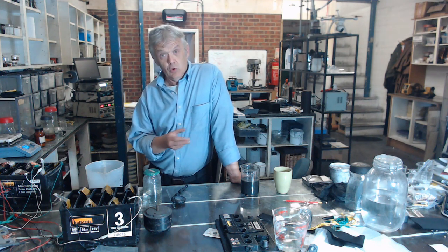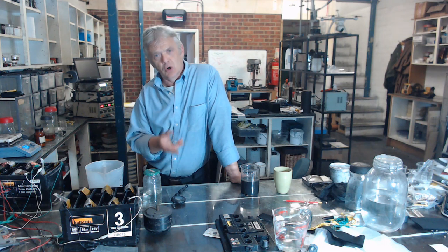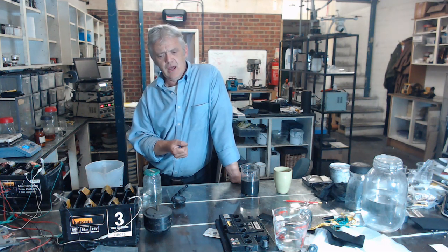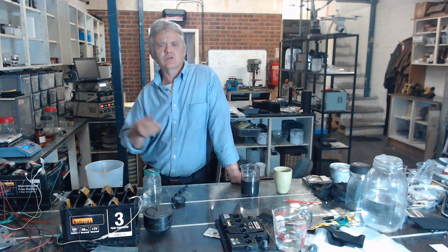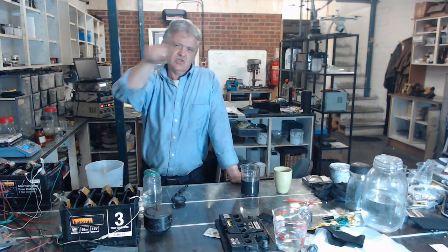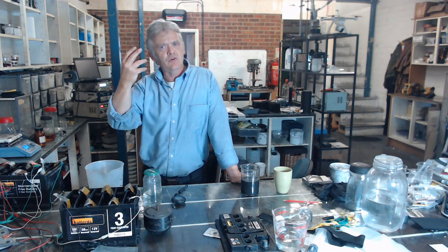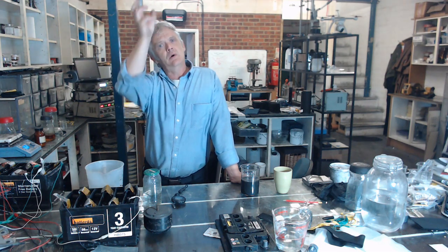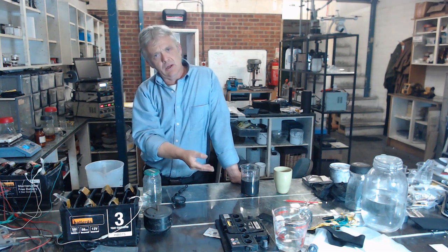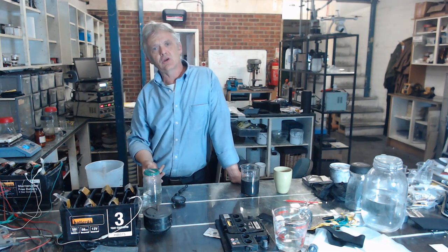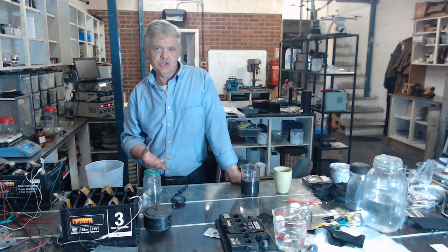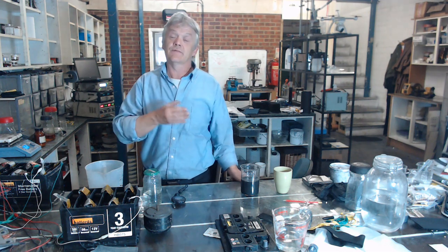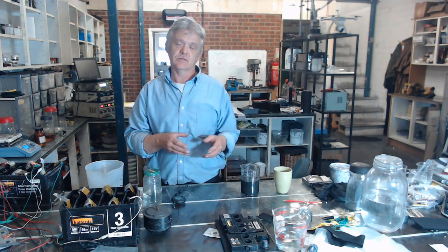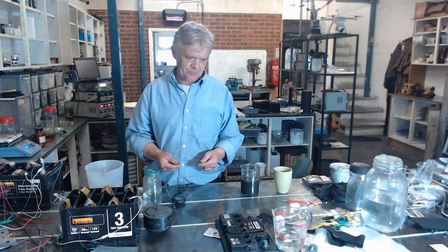Now obviously it uses a lot of water, so sometimes it's not appropriate to do that, and they use an air system where they crush it to a certain size, put it through like a zigzag, blow air over it, and the graphite flakes will go over there into a cyclone, collected at the bottom, and the heavier stuff drops out. And that air classification can be used instead of the first flotation, and then you do a second flotation. So it cuts down an awful lot of that.